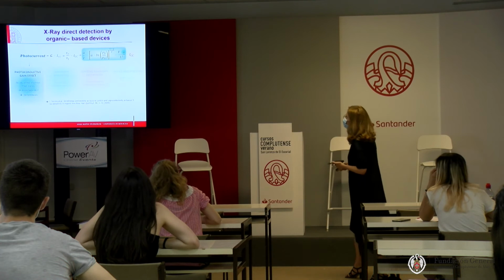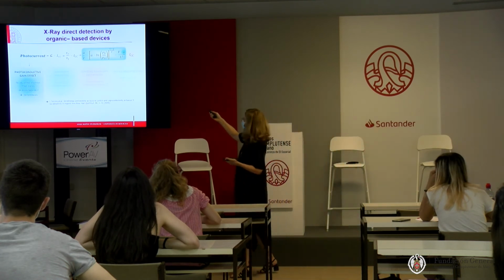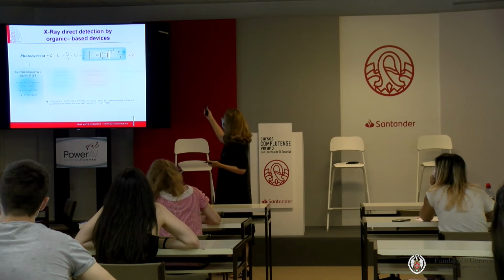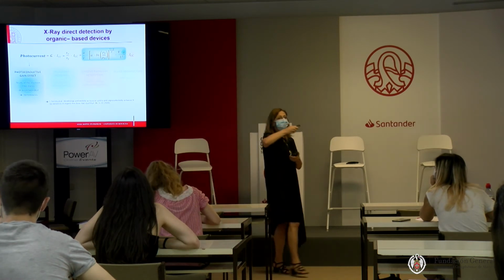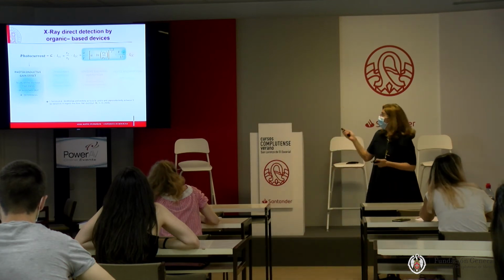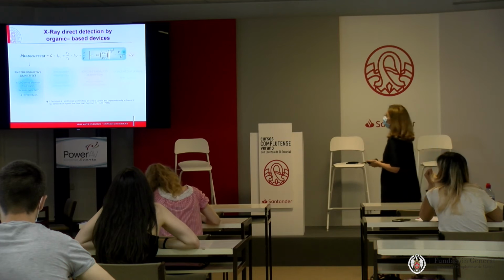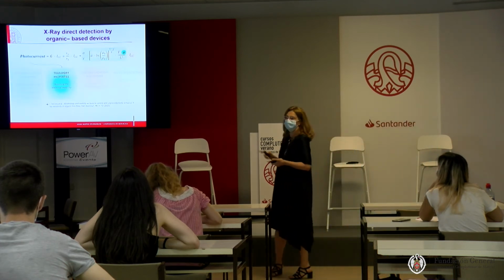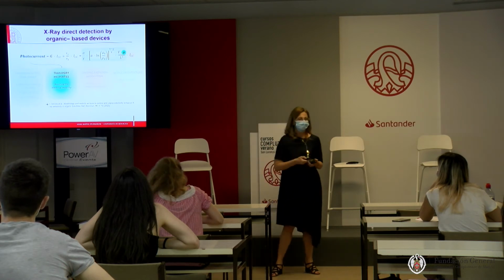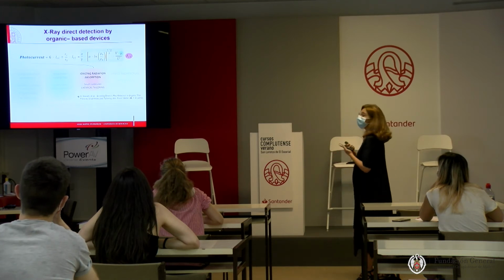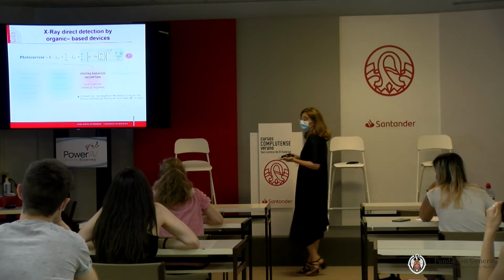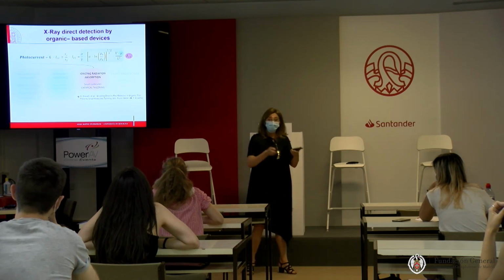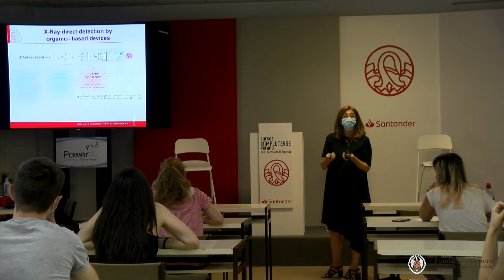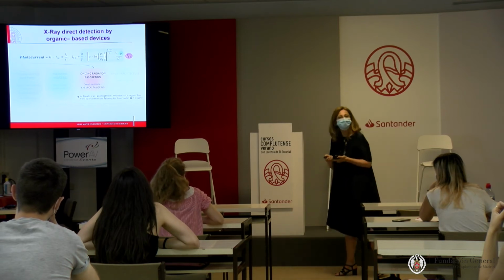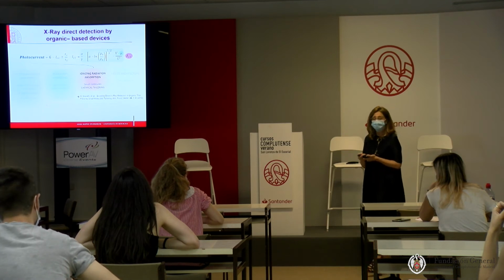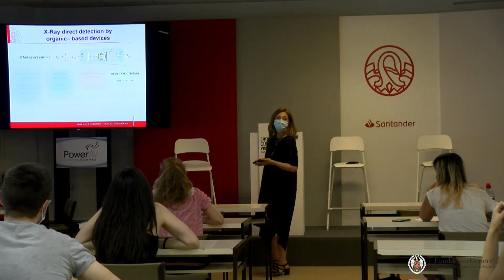This is probably more clearly stated here. You see the photocurrent, gain times collected current, which depends on these two, transit time and recombination lifetime. In order to increase this photoconductive gain effect, we can operate on the transport properties. You see, it depends on the mobility. We can operate on the absorption of radiation, because the greater the atomic number, the greater is the stopping power for X-rays. So we can change the molecule, because chemists are very good in modifying these solution depositable organic molecules. Or we can change the device architecture.